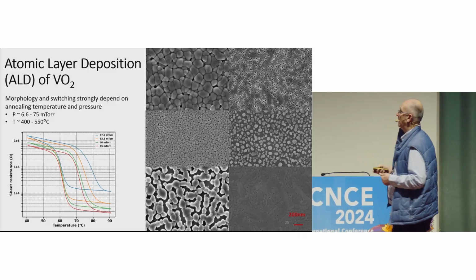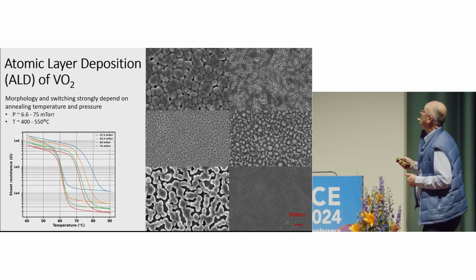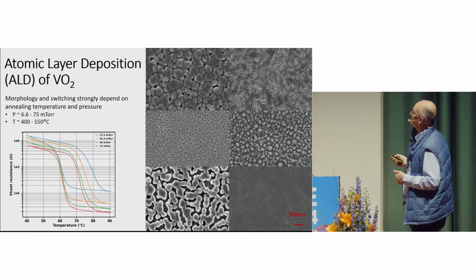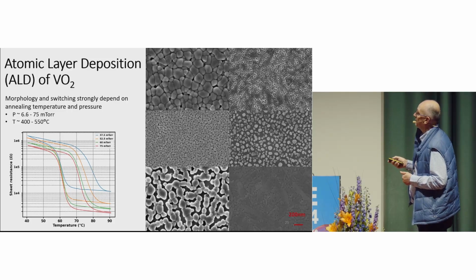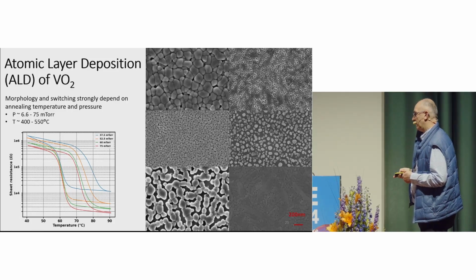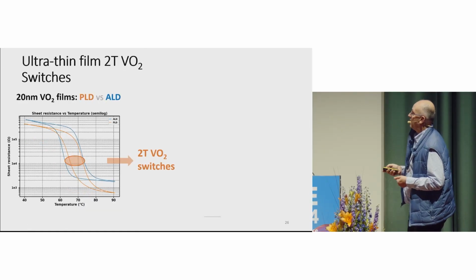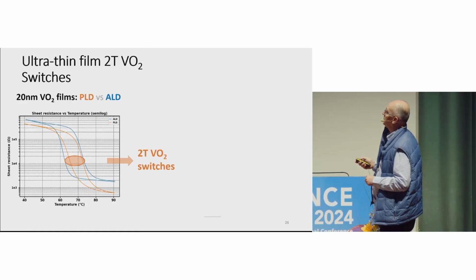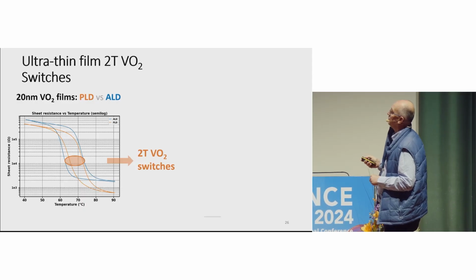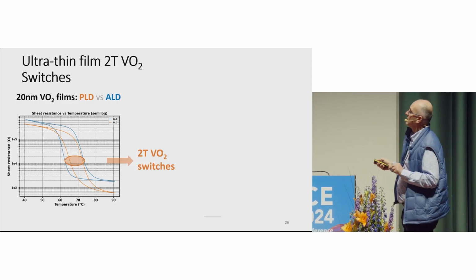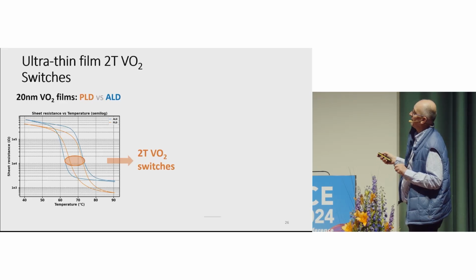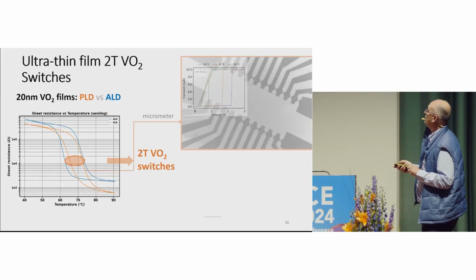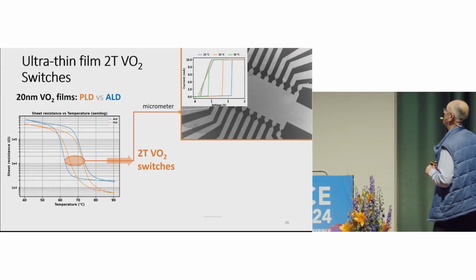We are not yet there, but we are at 2 orders of magnitude and something. And we can structure the films in different ways depending on the annealing temperature and by playing with the temperature of the substrate. So now I want just to show you what can be achieved. This is a 20 nanometer VO2 film, so it's extremely thin. PLD is the best material we have now in the lab. ALD is the one that is coming close to it. And here I want to show you different types of devices we are building.